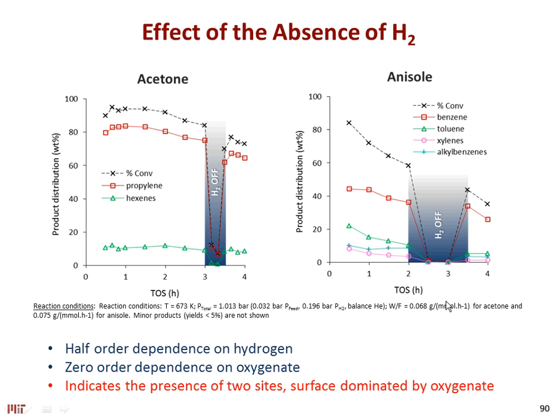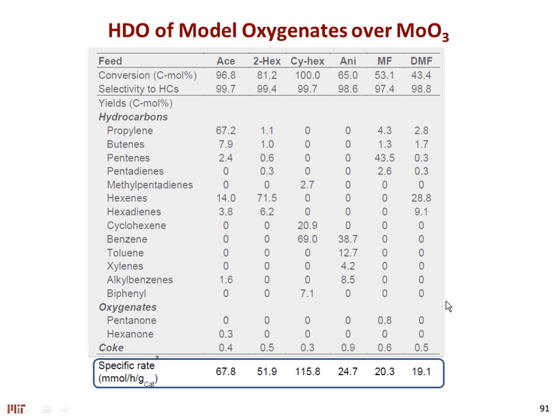So what we start seeing is that perhaps we actually have two catalytic sites, one responsible for the hydrogen dissociation, one responsible for oxygenate adsorption, and we're still trying to deconvolute what is going on with this particular surface. Something that was very intriguing to us is that you look at these rates, imagine the number is close to 100, and in this case, just remember the number 100.